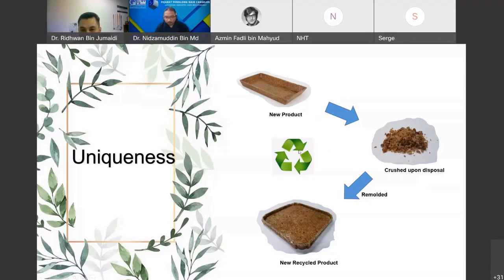However, for this material, even though it's starch based, according to my experience in working with it, it can be crushed to become a pellet like this, and then it can be remolded. You put it in the mold, and then we press it again to produce a new recycled product. So this plastic from plants is not only biodegradable, but also recyclable. So it has two very important characteristics in environmental preservation. It's biodegradable and also recyclable, and of course the source is renewable.